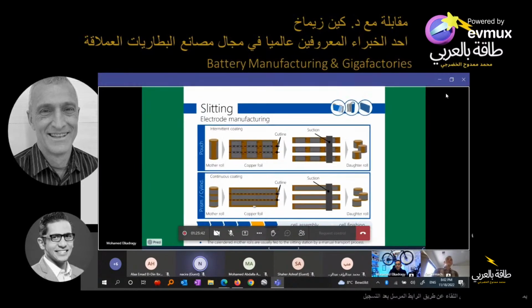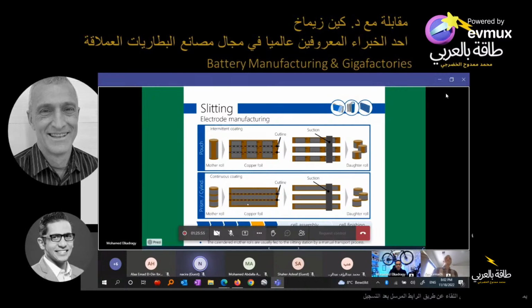So the slitting, generally, yeah, I mean, this is reasonably accurate. When you're coating, for instance, take that lower lane where it says prismatic and cylindrical, and you see that the coating is actually in little lanes. You can do that, or if you're doing prismatic, you might just have one lane, but then the left side would be an electrode and the right side would be too, and you'd slit it down the center. Now remember, when you're coating these things, you'll have high edge problems, you'll have low edge problems, you'll have width problems. All of this stuff needs to be in specification.